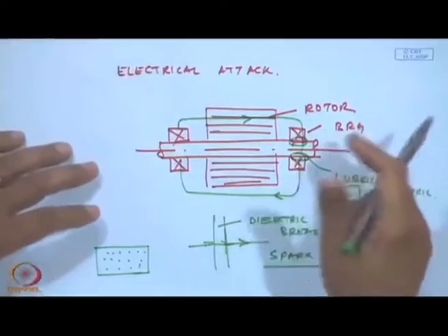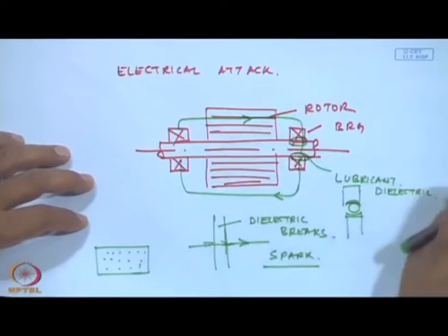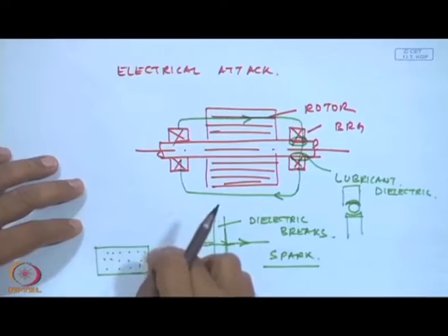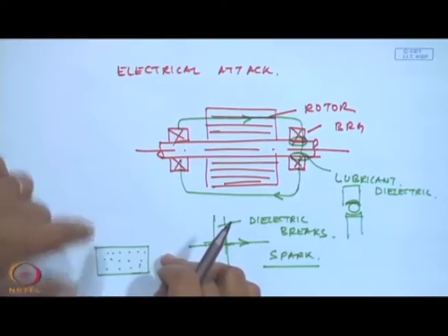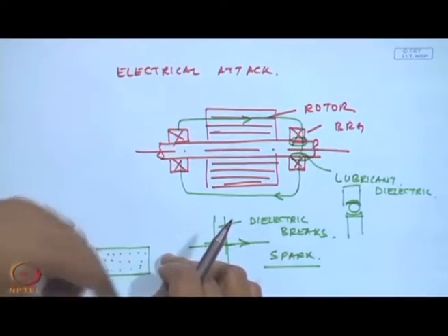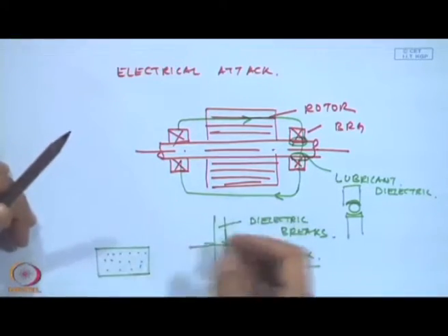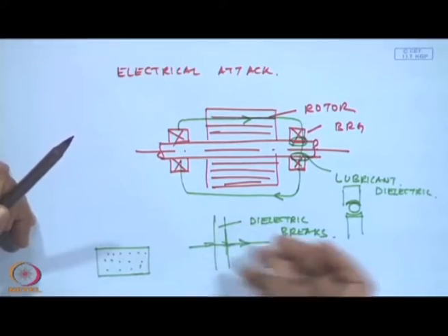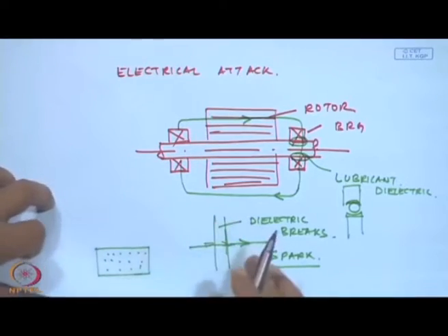Okay, the usual way to avoid it is to have good grounding. If you ground it, this does not happen. I will show you some. So, but then these are responsible for the initiation of the pitting, and once the surface has got pitted, because of load and temperature they are weakened, and then with time this small pitting will become large, scouring will occur, and then large chunks of the material are going to get eroded. So, surfaces are going to get worn out again.